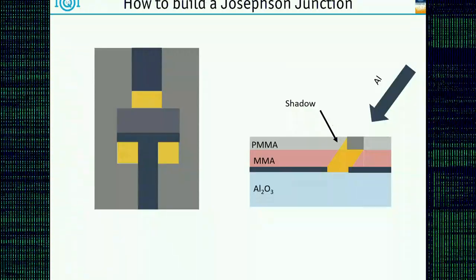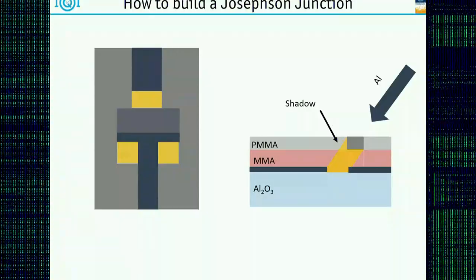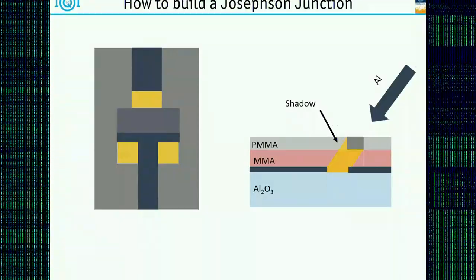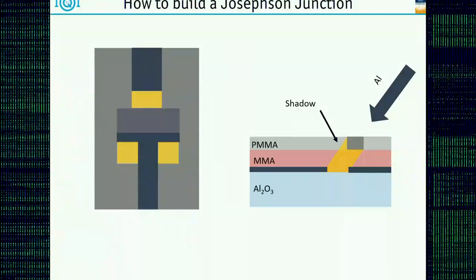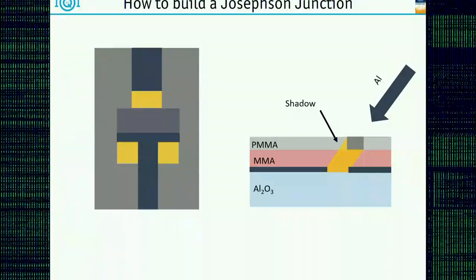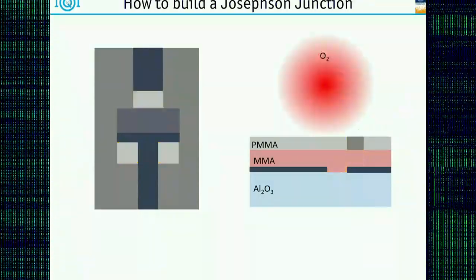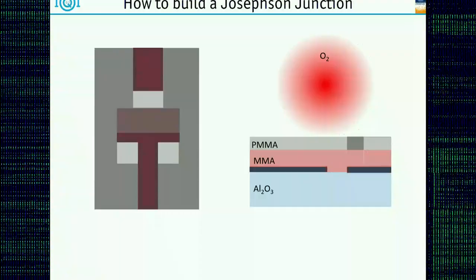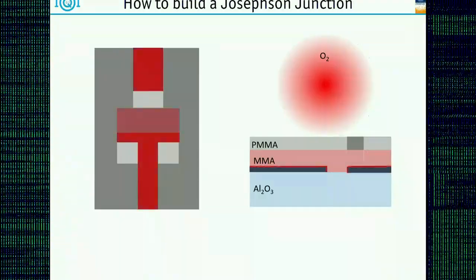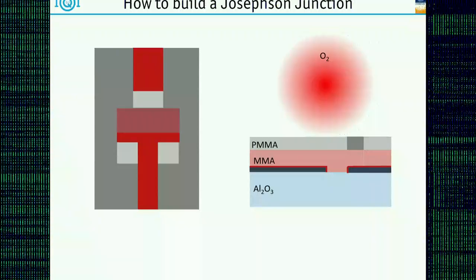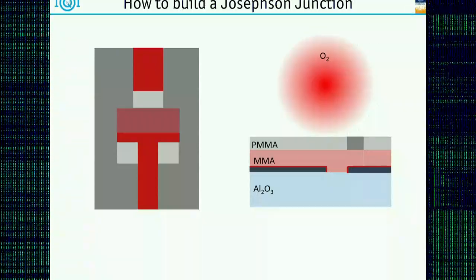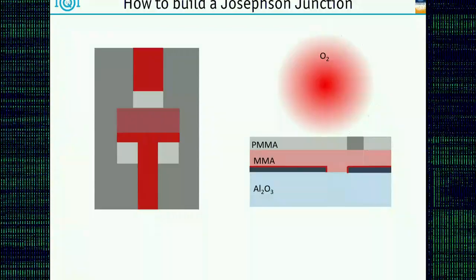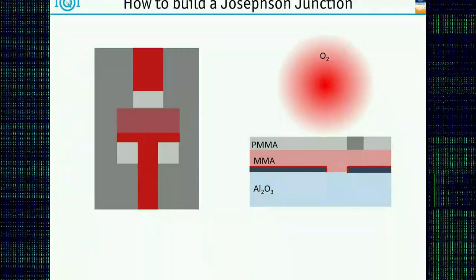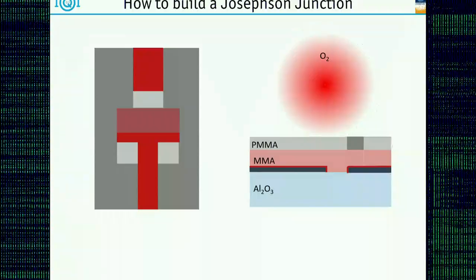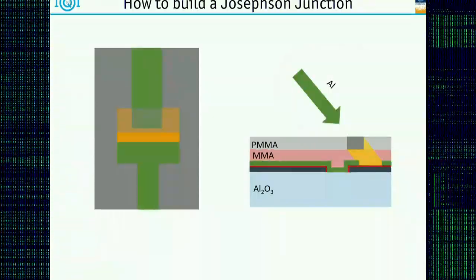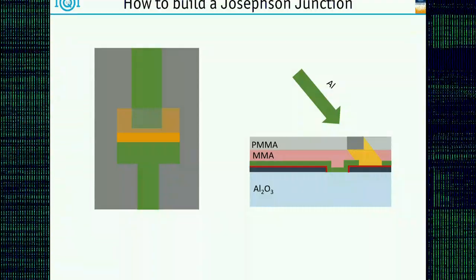What we can then do, say we want to build a Josephson junction, what we have to get is a very thin insulating barrier. And for aluminum, I already said this is very easy to do. All I have to do in my chamber is put oxygen in, and then over time an almost self-limiting aluminum oxide film grows. If I do it right, it will be about a nanometer thick. Now all the aluminum is covered in a thin layer of aluminum oxide. And now with the second aluminum evaporation step, I've actually created my Josephson junction.